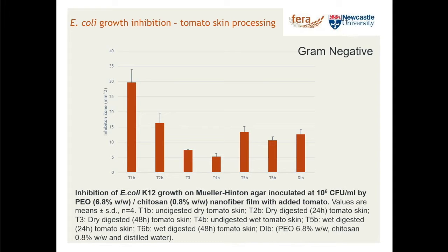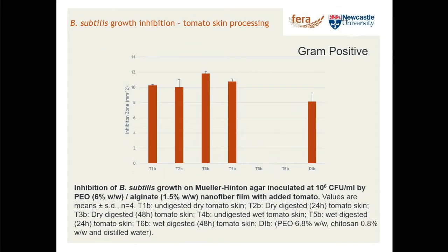So this is inhibition of E. coli, which is a gram-negative bacterium. So we need to try it on a different type, a gram-positive, and so we've used as an alternative Bacillus subtilis as a representative species just to see what we get. And again, we tend to see the same sort of thing. We get inhibition. The way in which the tomato skin's been processed didn't really seem to have a great deal of effect. But in a couple of cases, that's not totally true.